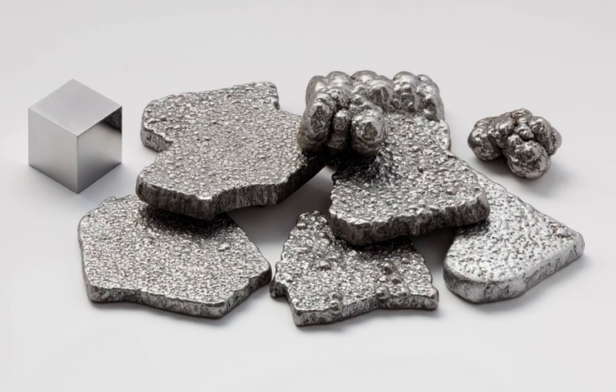The text accompanying the image in this subsection discusses this situation using more technical language. The elemental metals have electrical conductivity values of from 6.9 times 10^3 S per centimeter for manganese to 6.3 times 10^5 S per centimeter for silver. In contrast, a semiconducting metalloid such as boron has an electrical conductivity of 1.5 times 10^-6 S per centimeter. With one exception, metallic elements reduce their electrical conductivity when heated. Plutonium increases its electrical conductivity when heated in the temperature range of around -175 to +125 degrees Celsius.